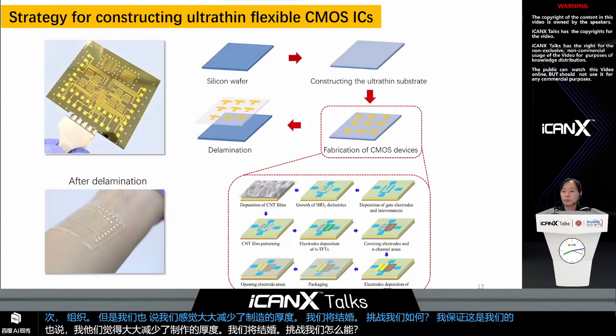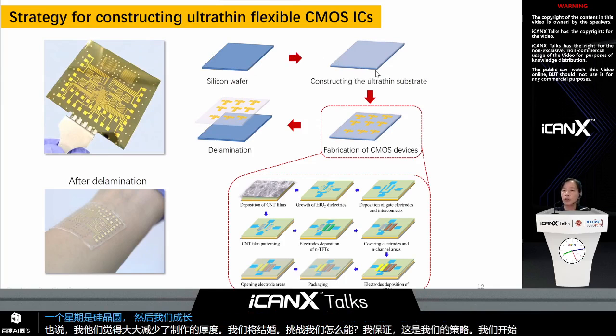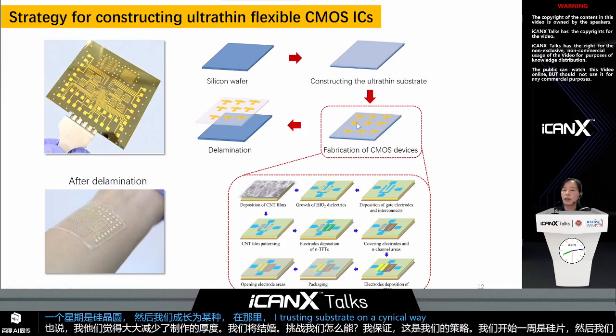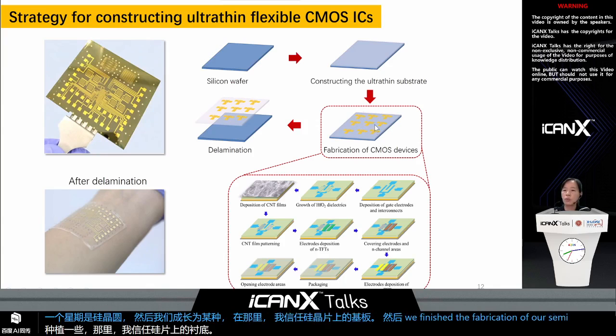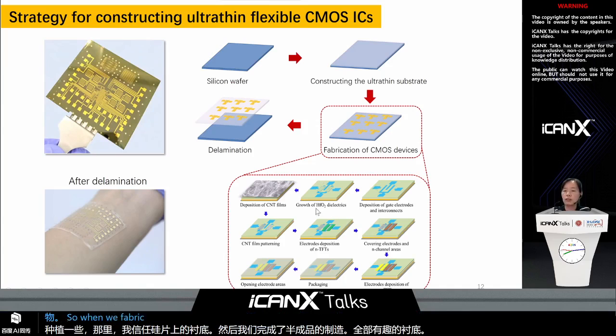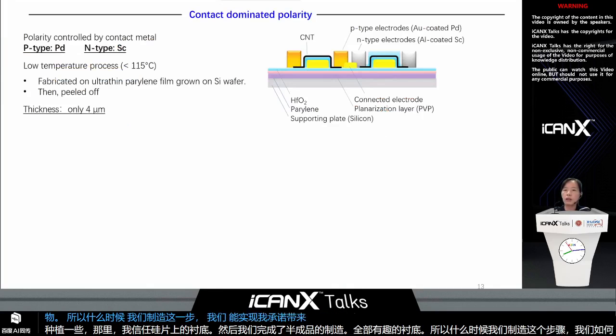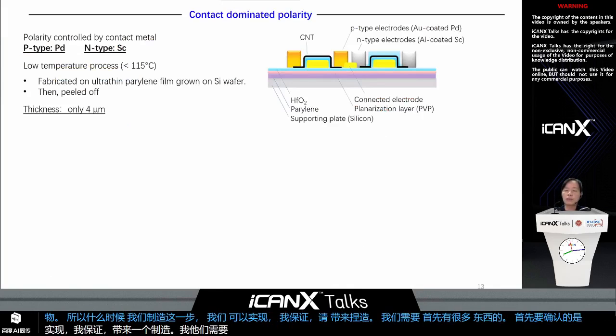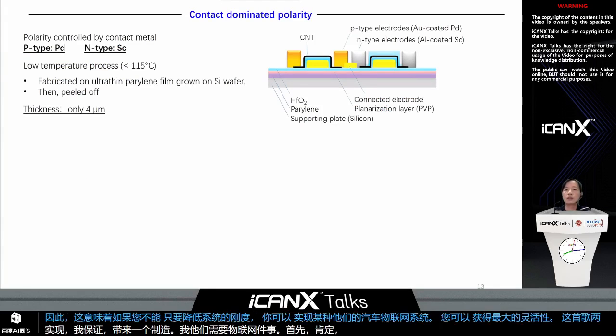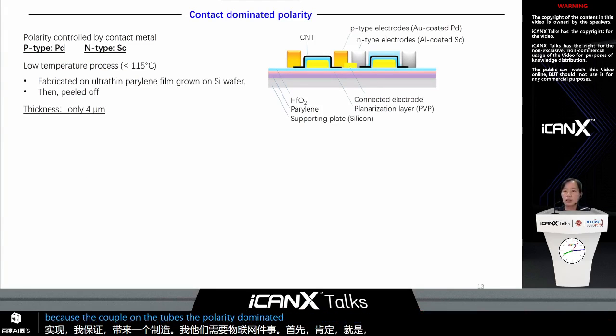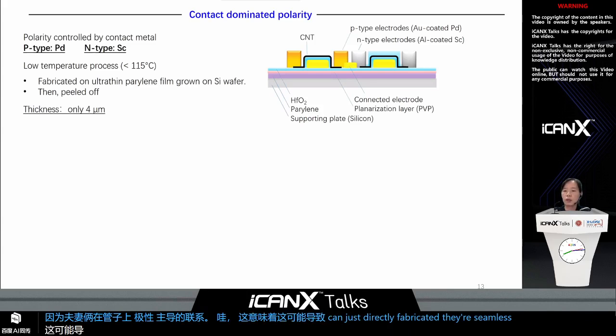Here's our strategy. We start with a silicon wafer, and then we grow an ultra-thin substrate on the silicon wafer. Then we finish the fabrication of our CMOS devices on the ultra-thin substrate, and then we delaminate the system from the silicon wafer. During this fabrication, we did a lot of things to achieve high performance. The first thing I mentioned is that in carbon nanotubes, the polarity is dominated by the contact, so we can directly fabricate CMOS on the ultra-thin substrate.